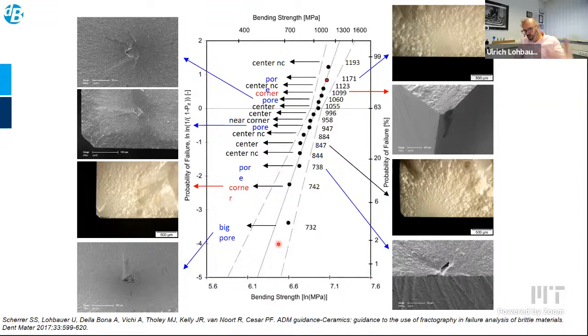But we can go much further once we analyze every single fractured surface. And we can say, okay, the fracture is emanating from a processing defect at the edge, for example, an internal microstructural defect, a surface defect, a processing defect. Everything's possible. So we can separate the reasons for failure emanating from the processing of the material or emanating from the microstructure.